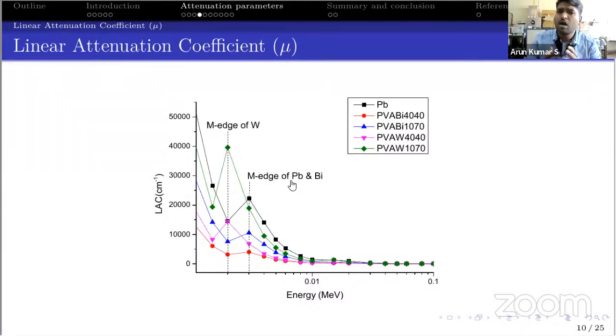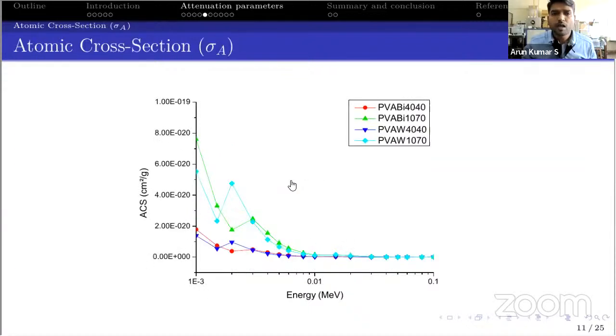Here also we can observe and confirm that the tungsten PVA composite has very good radiation resistance compared to the lead and bismuth PVA composites. The next one, the atomic cross section, is also confirming that compared to the bismuth PVA composite, the tungsten PVA composite provides much more radiation resistance and opaqueness. So it is showing that it is a very good material at the lower energy. But when it comes to real-life use, we need a material for the higher range also.